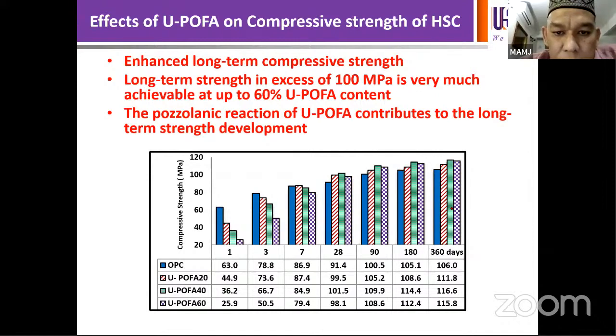So in this particular case, for the palm oil fuel ash concrete, okay, the observation is basically enhanced long-term compressive strength. In excess of 100 megapascal is very much achievable at up to 60% U-POFA content, okay? And then the pozzolanic reaction of U-POFA contributes to the long-term strength development here, all right? So we can see that the material is efficient, okay? And it's able to improve the long-term strength, but not the early strength.